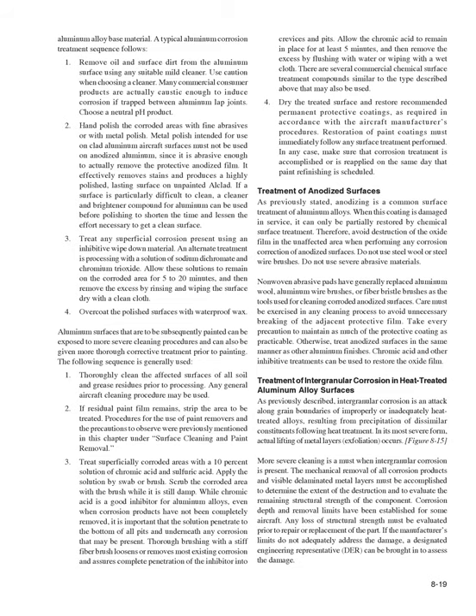As previously stated, anodizing is a common surface treatment of aluminum alloys. When this coating is damaged in service, it can only be partially restored by chemical surface treatment. Therefore, avoid destruction of the oxide film in the unaffected area when performing any corrosion correction of anodized surfaces. Do not use steel wool or steel wire brushes. Do not use severe abrasive materials.